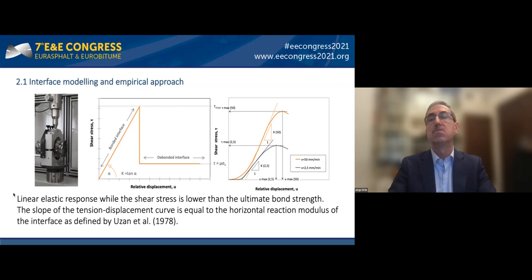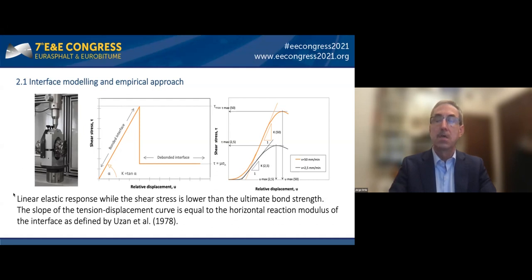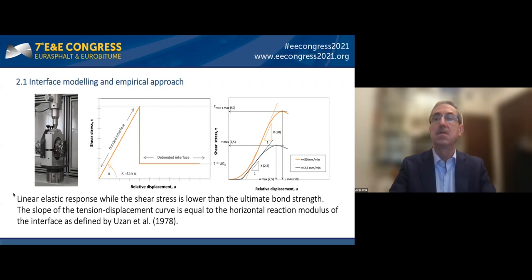The Uzan model allows sensitivity analysis of the effects of different interface conditions represented by different k values. However, the empirical approach to k is somewhat more complex — the slope of the tension-displacement curve varies with stress, forcing selection of the load level at which the target is measured. The viscoelastic nature of the interfaces also provides behavior dependent on temperature and load time, so realistic estimation requires proper simulation of typical load times and temperatures.